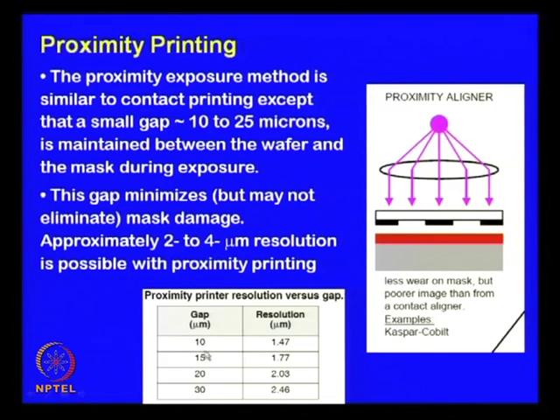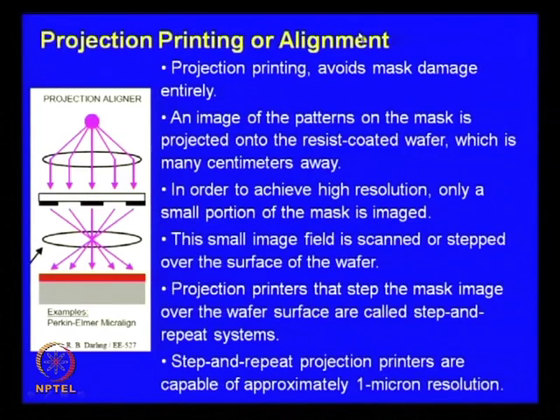So, let us say from a gap of 10 micron, where the resolution in a particular case was close to 1.5 micron, it goes roughly all the way up to something like 2.5 micron for a 30 micron gap size. So, this is what proximity printing mode is. The most widely used, and it also comes with its own advantage, is the so-called projection printing mode.